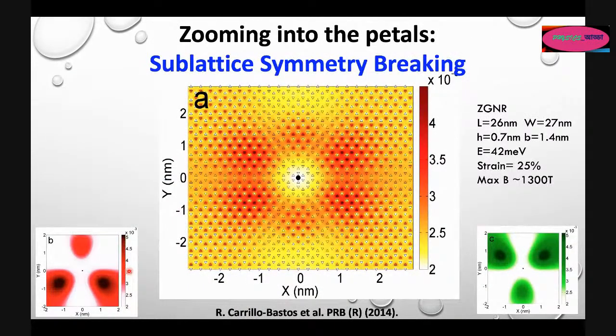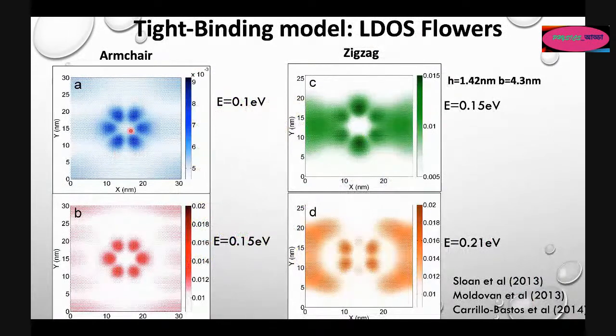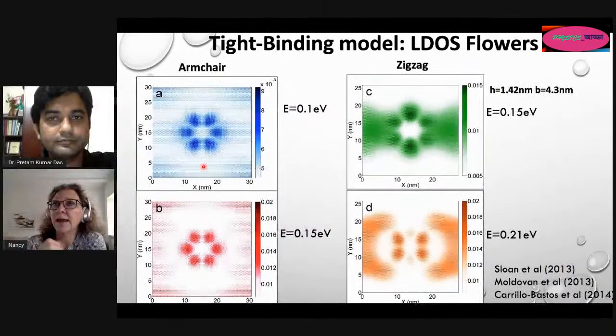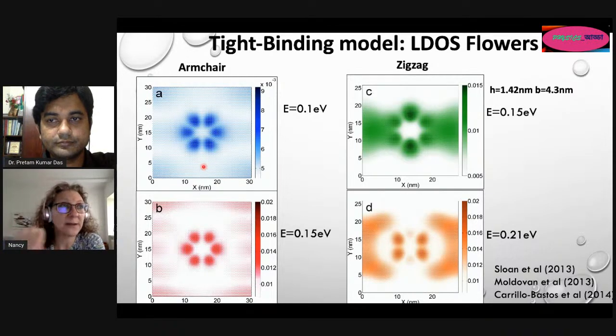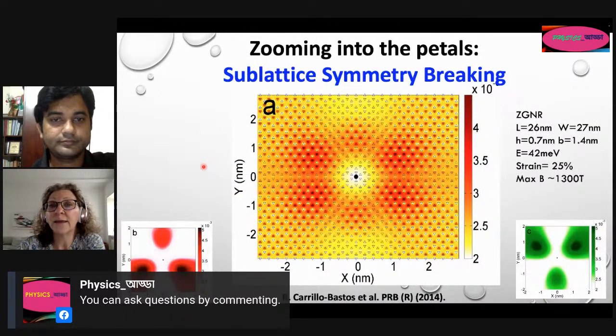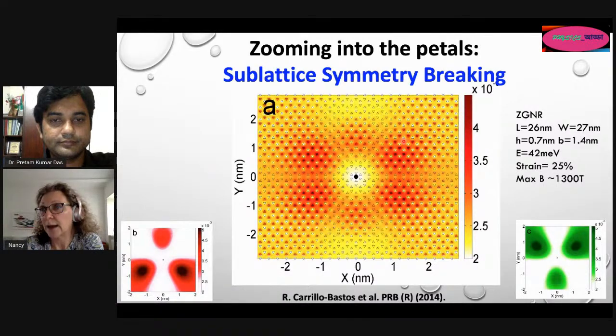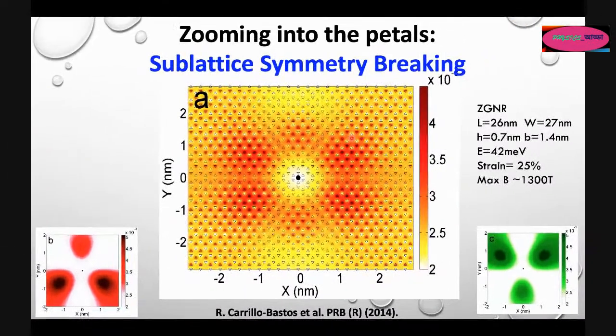So we said, okay, but this has a shape of 6 petals, and this will give me a hexagonal symmetry, a perfect hexagonal symmetry. So I would have expected to see in the STM images a perfectly defined hexagon, something that has a 6-fold symmetry. However, what was observed was a 3-fold symmetry. So how can I see that? So what we did, because we have the Hamiltonian written in terms of this pseudo-spinor, was to see what happens with the wave function of the electron sitting at each sublattice separately.